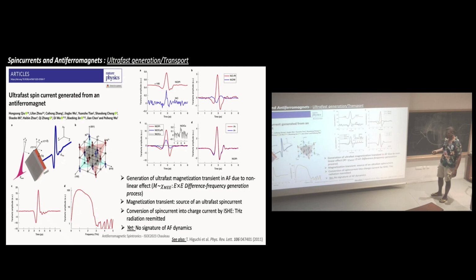So okay, they have only NiO with platinum. If there is platinum, it is enhanced, some kind of spin current going through the platinum, but there is not yet any signatures of antiferromagnetic resonance, because they have only this kind of broad ultra-fast generation, which is actually due to some kind of optical rectification from the pump.